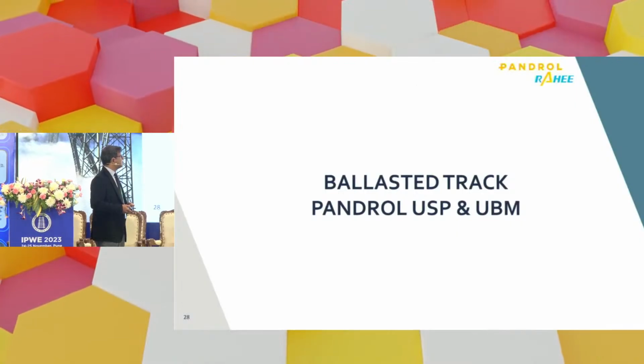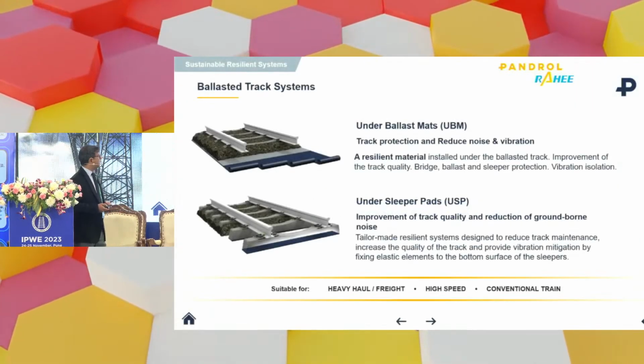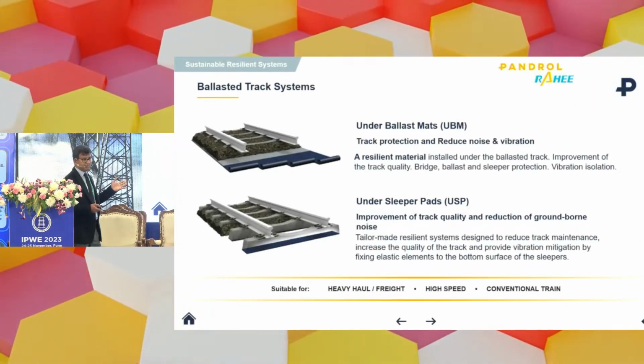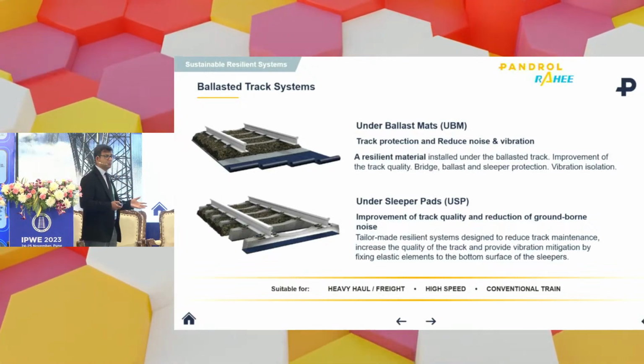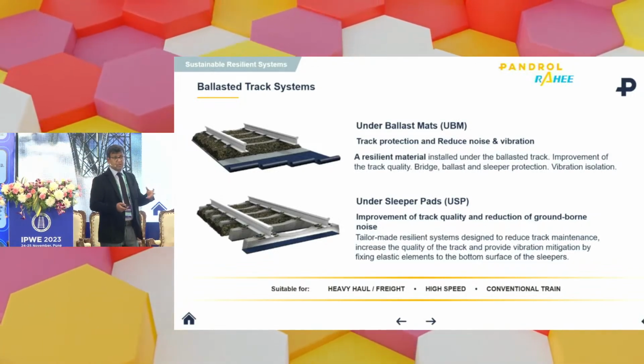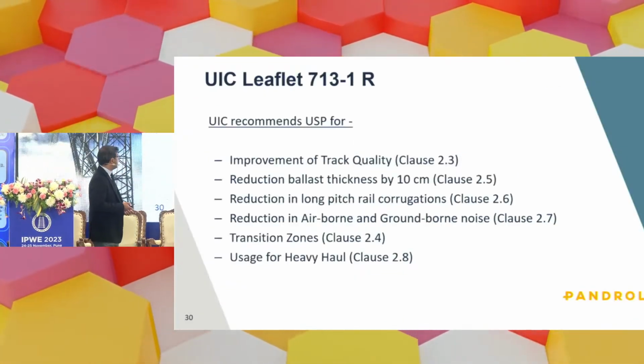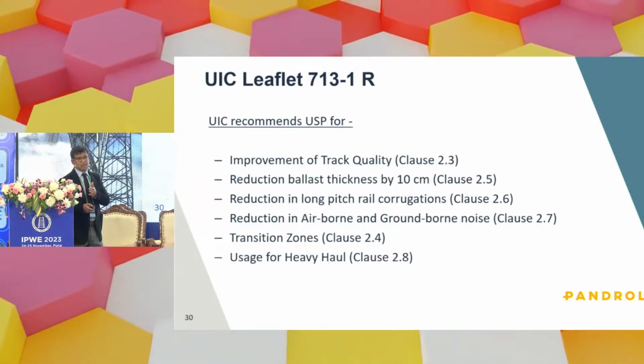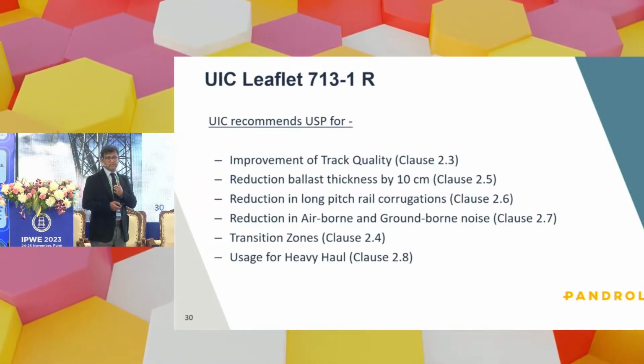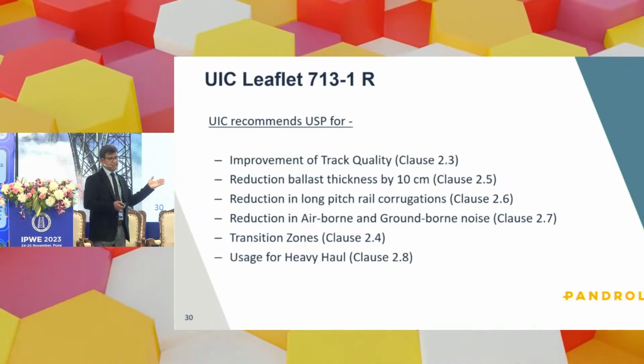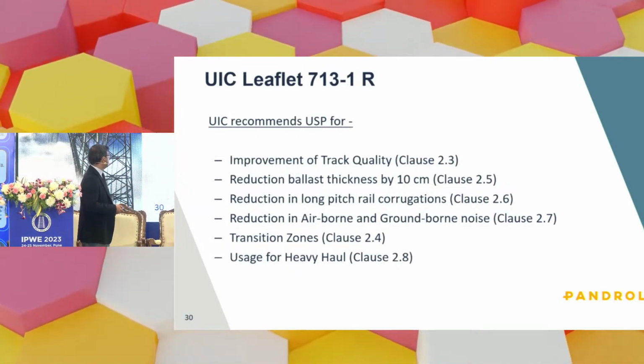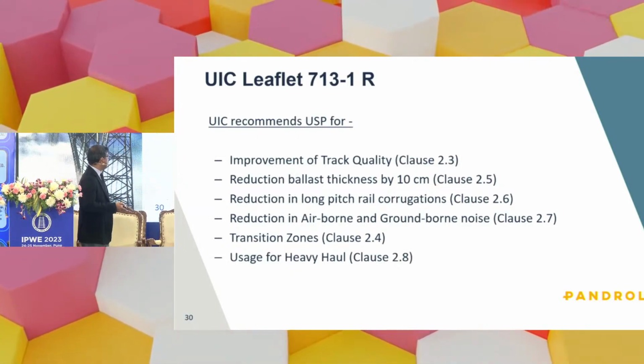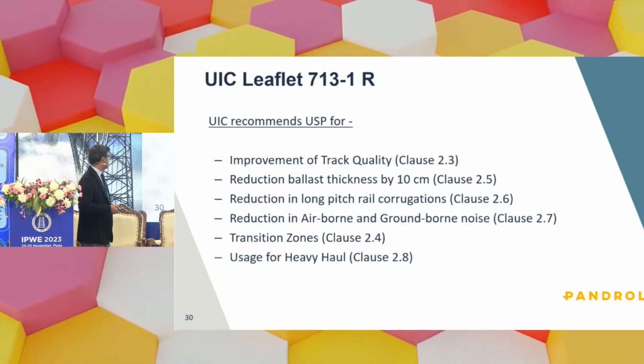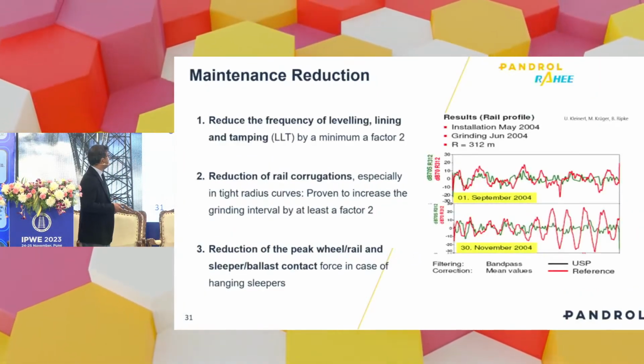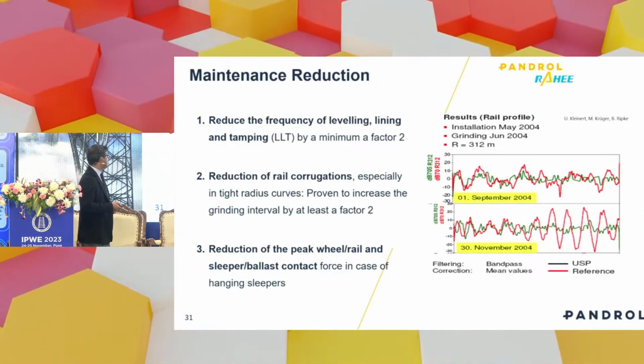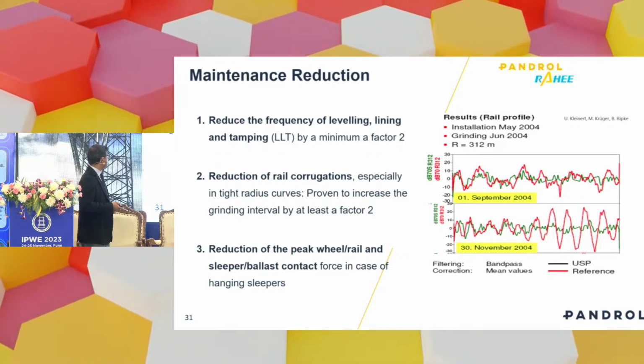These are some of the projects. Looking into ballasted track solutions, we have undersleeper pad and under ballast mat. These are, again, solutions which can provide resilience into the track. One UIC study says that you can remove 100 millimeter of ballast from the track by introducing these solutions. By deploying these solutions, you can have reduction in ballast thickness, long pitch rail corrugation, and airborne and groundborne noise. Maintenance is reduced: the frequency of leveling, lining, and tamping is reduced.